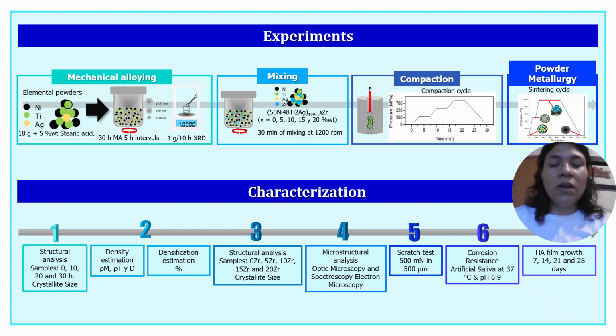compaction cycle of 300, 600, and 900 megapascals with a dwell time of 5 minutes at each pressure, aiming to increase the relative density of the samples. Finally, the samples were sintered at 1000 degrees Celsius for 5 hours and cooled inside the furnace.